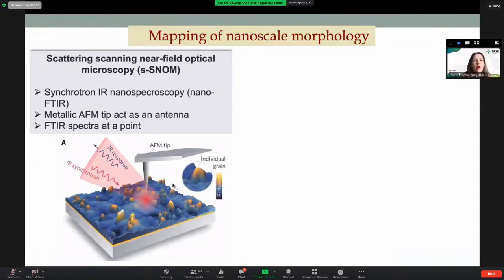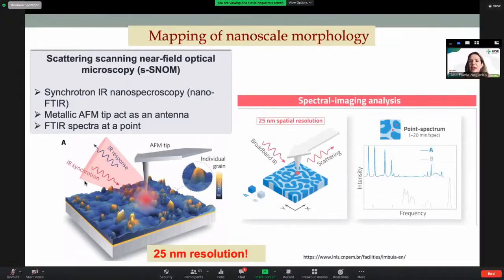So we couple here AFM with the infrared from the synchrotron, and we collect the scattering of the infrared light from the sample, with a resolution of 25 nanometers. I think this kind of technique is really important for those working in the area of materials. We can have two different analyses. You can have a broadband spectrum, meaning a complete image of the infrared response of the film, but also you can choose one grain.